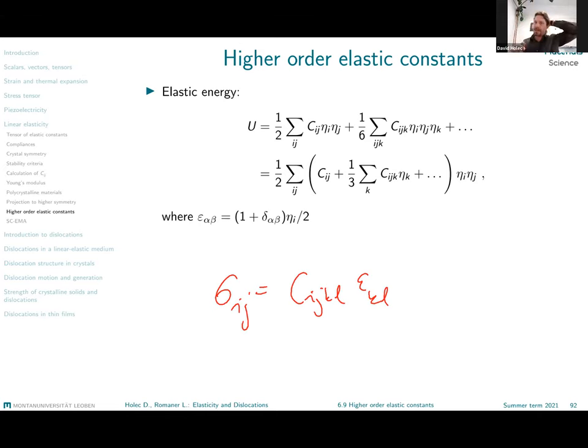So if we now say that we do not know the elastic relationship, but we know how the total energy changes with respect to the applied strain, so we can estimate the elastic energy as a function of strain. Now we can obviously write the Taylor expansion of this energy as a function of strain. If we cut the Taylor expansion after the quadratic term, we are in the linear elasticity regime. But we can also include higher order terms. And that would lead to third rank tensor elastic constants, or so-called third order elastic constants. Third order because they now have three indices and they depend on three components of the strain tensor.